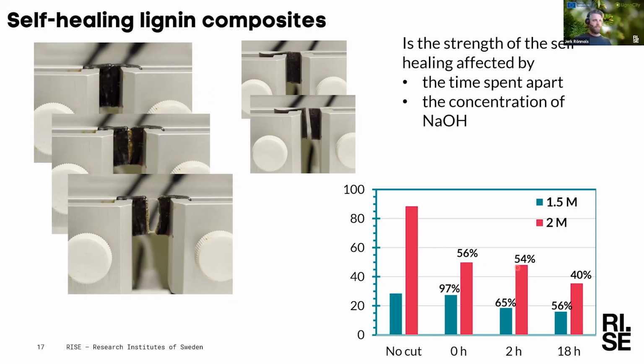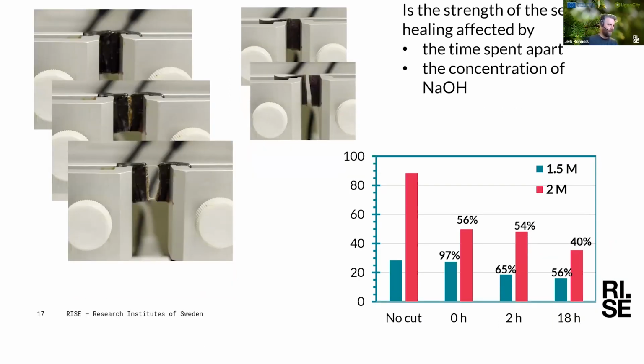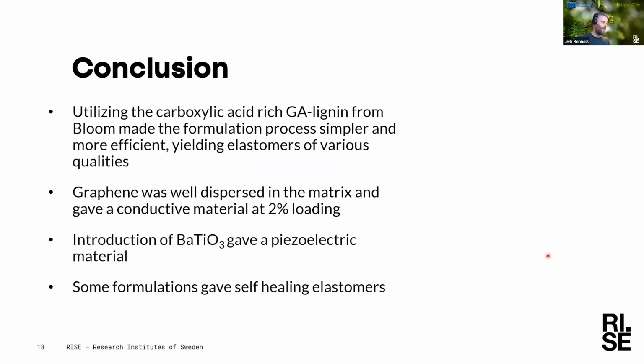And after leaving the pieces apart for 2 hours, the strength is sort of the same. After leaving it apart for up to a day or 18 hours, it reduces somewhat, but it still heals to a quite significant amount. And we could also see that the concentration of sodium hydroxide apparently plays a role in how strong these are. I'm rushing by this, sorry for that, but we can have more discussions on that later.